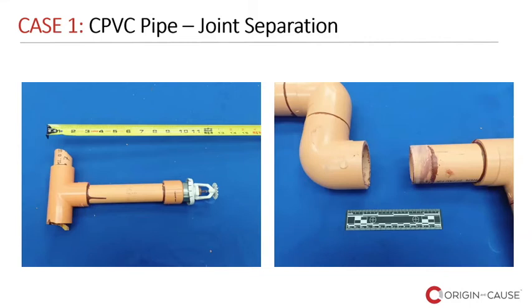So in the example above, I am showing a pipe that's separated from the fitting. And amongst other observations, some important issues that we found during the investigation were that the cut end of the pipe was not square, and that there was a lack of or inadequate chamfering or beveling of the pipe end. So these two are critical, and the manufacturer points these out very clearly in their instructions, and for a good reason, right?